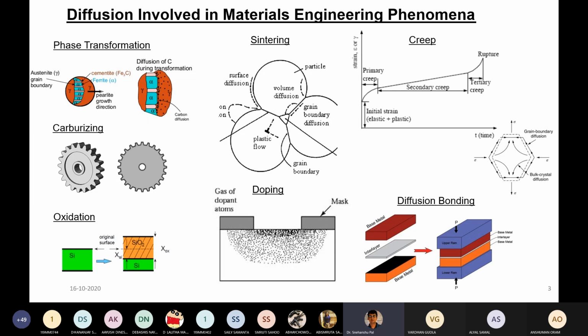because if you put a carbon atom in the tetrahedral void of the BCC ferrite phase, then an asymmetric elastic strain may occur, and that actually destabilizes it. So accommodating a higher percentage of carbon is not possible if you try to introduce the carbon into the ferrite phase. That's why, in order to do carburizing, you have to raise the temperature. The processing temperature generally ranges around 850 to 1000 degrees centigrade, and hardening is achieved by quenching after carburizing to produce a high carbon martensite structure. High carbon martensite structure.